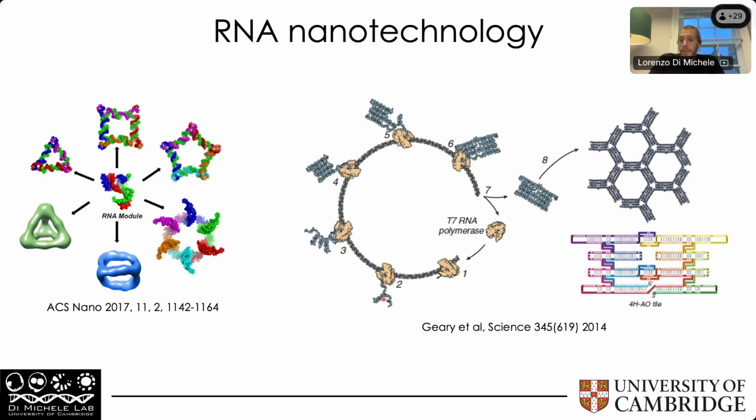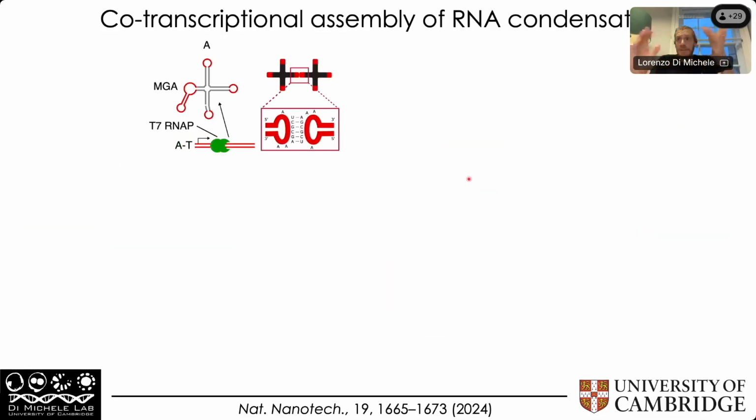So this is very powerful because it means that you can now express your RNA nanostructures, for example, within cells or within synthetic cells. Many people are interested in doing this, but it also makes the design of these structures a bit more complicated. You can't anneal your RNA nanostructures if you want them to fold co-transcriptionally within your cells or your synthetic cells. So the way in which you design them and the way in which you design them to interact with each other is a little bit different.